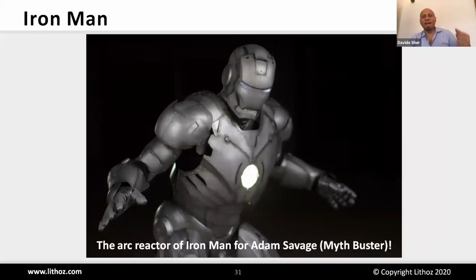What material was it? So, and back to part size. How thin can the walls be? Yeah, that's actually a good question. This is actually what we're working quite a lot on. So we were really able to make a complex structure, like something you see here, with strut thicknesses below 100 microns. So really thinner than a human hair. We even could go down to 80 microns in strut thicknesses, well below half of the thickness of a human hair. I think this is really unique. It is really a challenge, but we mastered it.